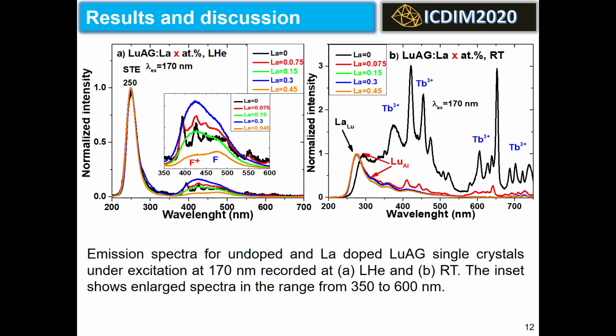The spectrum for undoped LuAG crystal recorded at room temperature shows noticeable emission of terbium-3+ trace impurity ions in the visible spectral range, which significantly decreases with increasing lanthanum content. Interestingly, the ultraviolet part of the spectra consists of a broad emission band centered at 292 nanometers for undoped and 275 nanometers for lanthanum-doped LuAG crystals. The luminescence at ultraviolet spectral range has exciton nature.